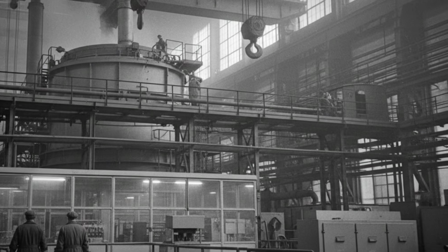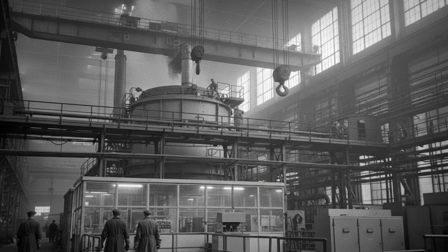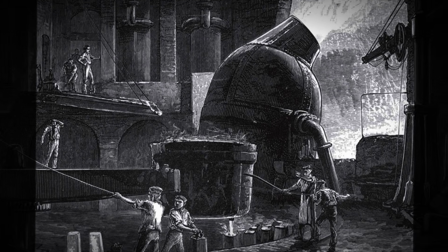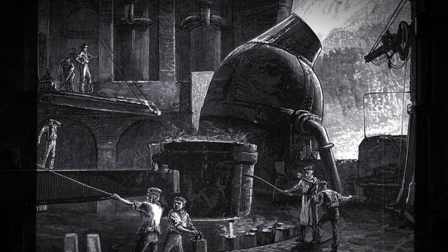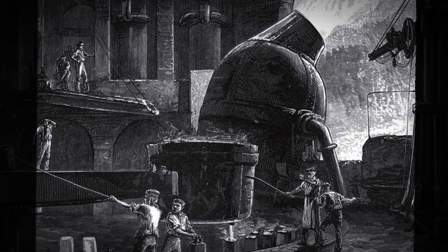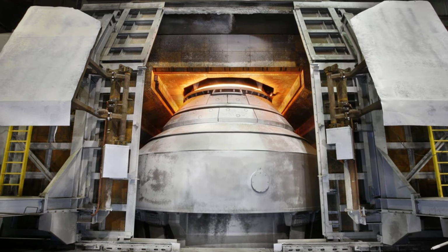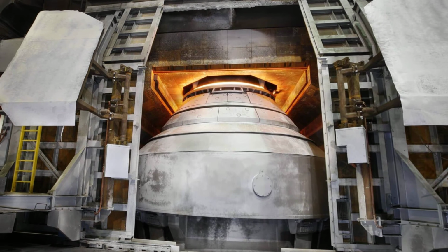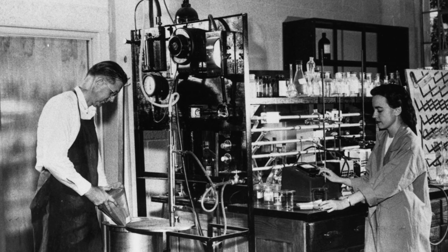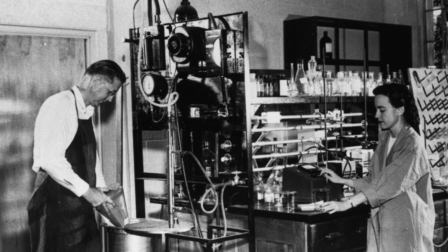The basic oxygen furnace, first used commercially in Austria in 1952, took the fundamental insight of the Bessemer converter, blasting oxygen through molten iron to burn off carbon and impurities, and improved it with pure oxygen instead of air, eliminating the nitrogen contamination that had been the Bessemer's weakness.